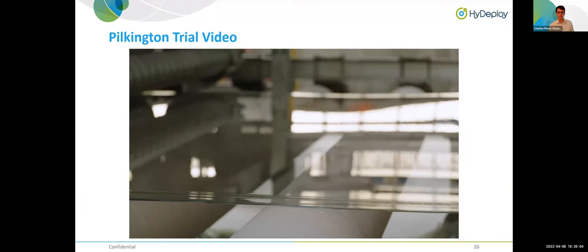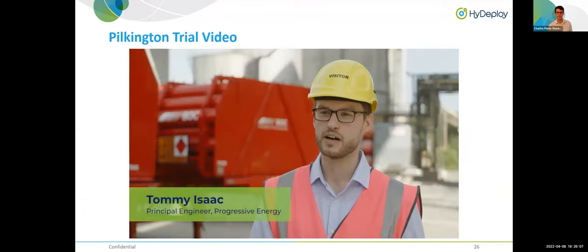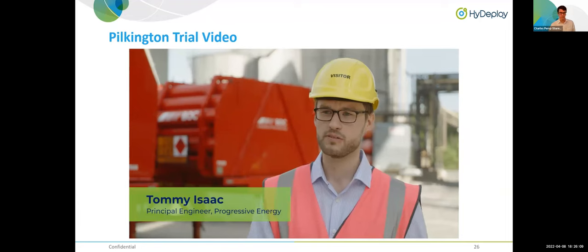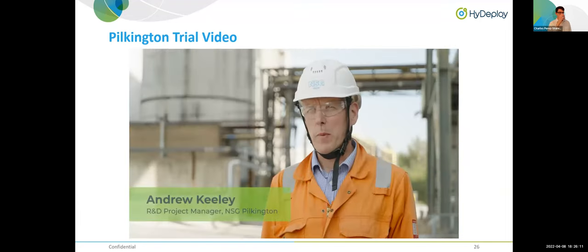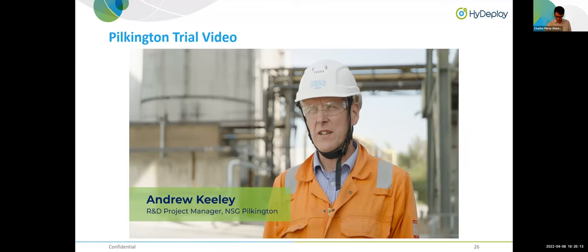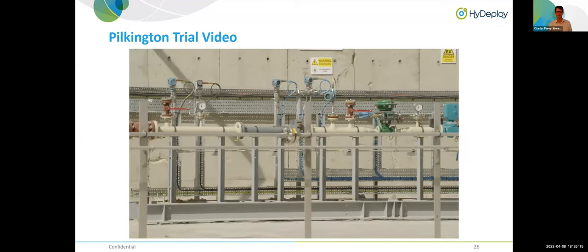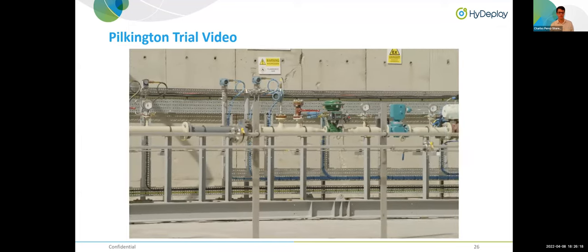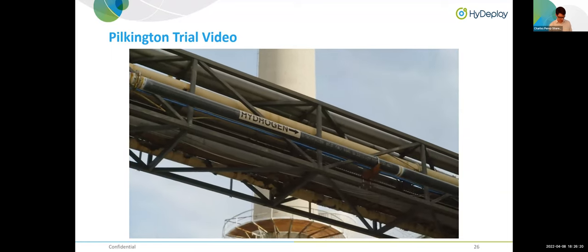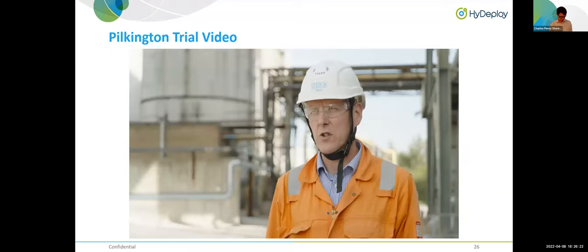The trial that's taking place here at Pilkington is to run a five-day trial for adding a hydrogen blend to the furnace here on site. What we're doing in these trials is we're blending 15% hydrogen into all the natural gas on the furnace. We're running these trials to assess the impact of the hydrogen on glass quality and furnace operation.